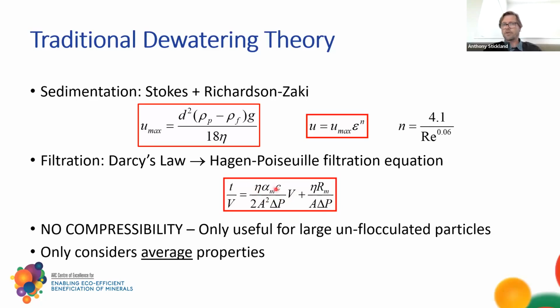So we've got some contribution from the cake, and that's changing with V because we're building up more and more cake as we filter, plus some contribution from the membrane. That's not changing as a function of time because that's just sitting at the bottom. Alpha m is capturing the rate at which it's going through, and that's called the specific cake resistance. Now, the assumption is made that it is a constant, or an average value across the whole cake. Unfortunately, measurements show that it is a function of pressure.